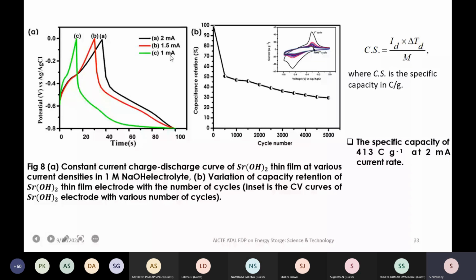Then part B, the variation of the capacity retention of the strontium hydroxide thin film electrode with the number of cycles. We have tested it up to 5,000 cycles, and one can see that it is lowering down. Up to 500 or 600 cycles it is going to 50 percent, but from 50 one can see the lowest one, about 39 or nearly 41, after these 5,000 charge discharge cycles. So that is also very necessary.